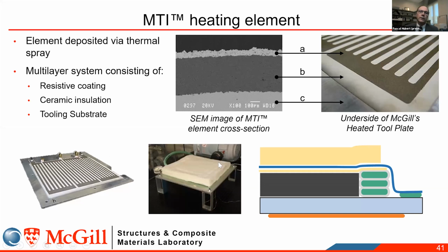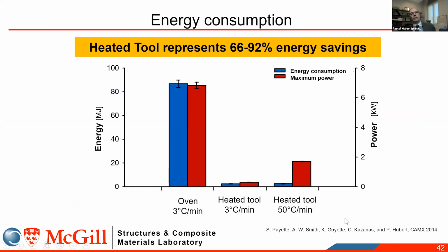And what you do here is that you just place your laminate directly on the tool. The heating element is underside. So you're heating the tool, and you have a layer of insulation on top. It's really the concept of barbecuing your composite. That's what you're doing. In terms of heating efficiency, it's really, really good. If you compare the energy consumed to cure a part in an oven compared to those heating elements, you can have 60 to 90% in energy saving. So this is great.